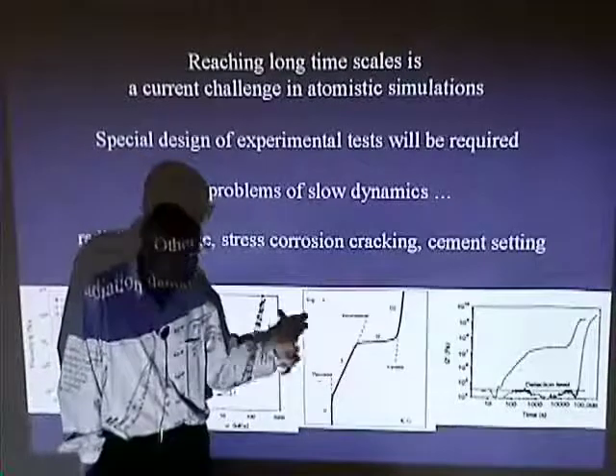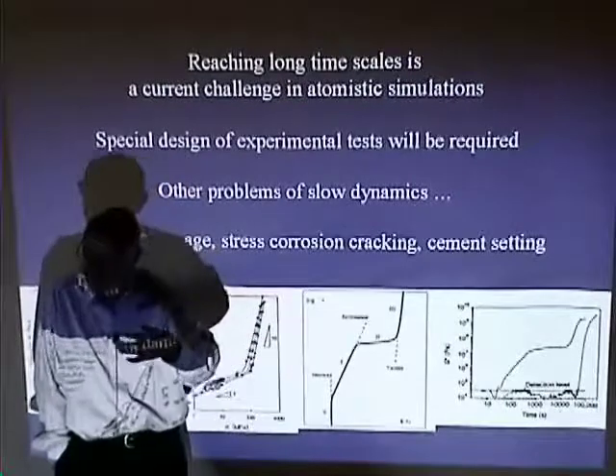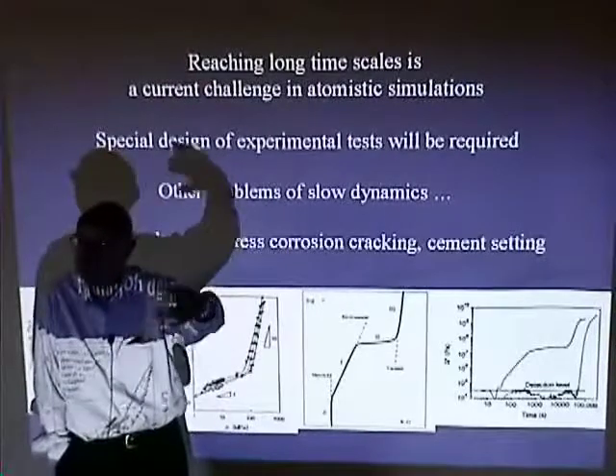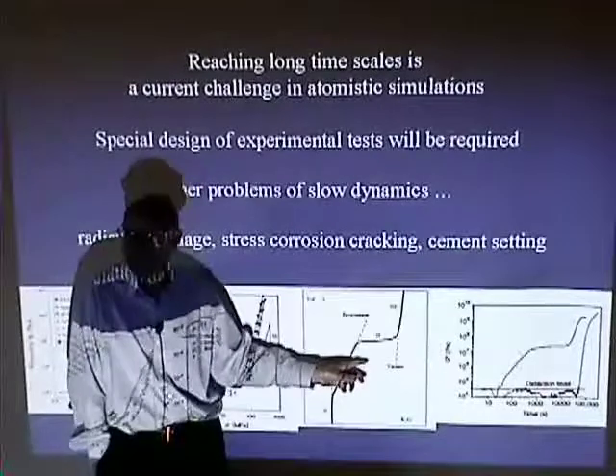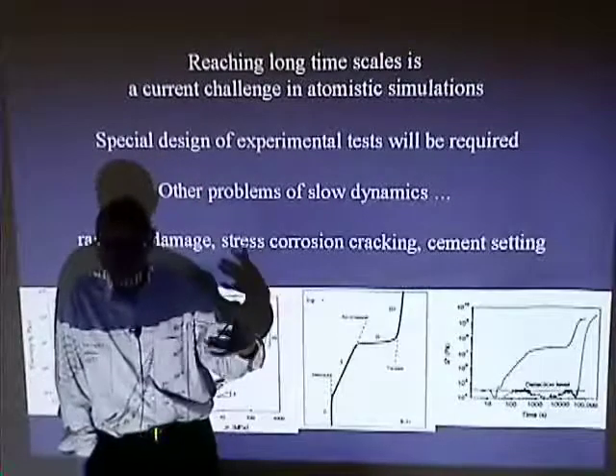And the mechanism in this case is that these corrosive agents not only make the cracks weaker at the crack tip, but once you exhaust them, you need more supply. They have to come from farther away, and that's transport control. So this incubation time now requires transport in addition to reaction, okay?